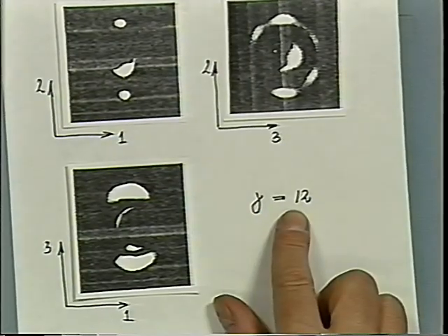If we go beyond that, we have data of shearing to 20 shear units, and there the order deteriorates. We are randomizing the hexagon structure, while still keeping the cylinder orientation for quite a while.